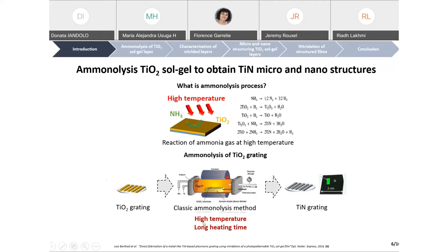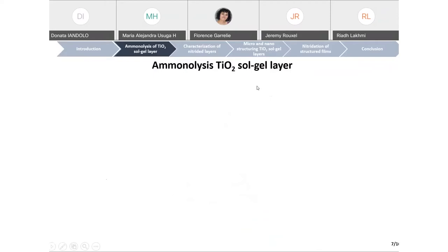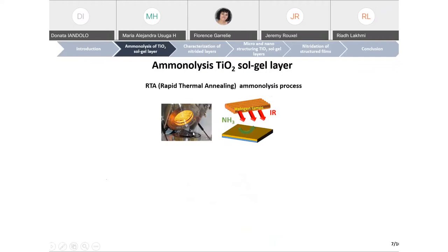So an innovative method is proposed to obtain titanium nitride micro and nanostructures. This method is the ammonolysis of a titanium dioxide sol gel layer with the rapid thermal annealing ammonolysis process. The RTA nitridation consists of heating with infrared flash lamps. The infrared flash is applied for a few seconds and over a lot of cycles. The ammonia gas reacts with the titanium dioxide to produce titanium nitride.